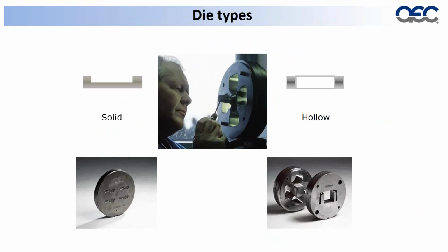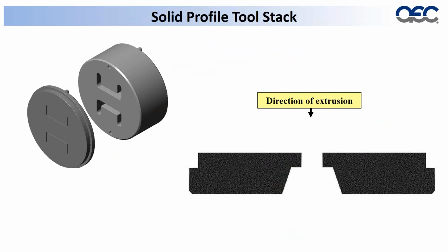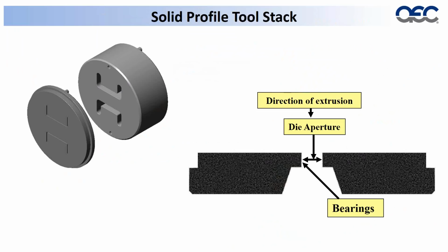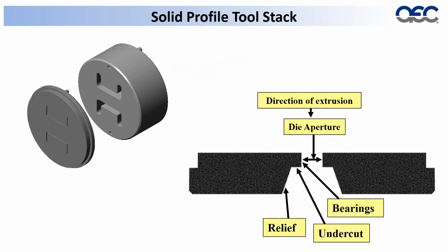So when we look at these solid profiles, what we see is the extrusion direction will be from top to bottom. The aluminum goes through the die aperture. Where it's going through that aperture, it's actually rubbing on what's called bearing, which is what controls the velocity, because aluminum loves to stick to steel. So that frictional work actually controls the velocity of different size apertures within the steel itself. And that essentially is what you end up with, a solid shape.